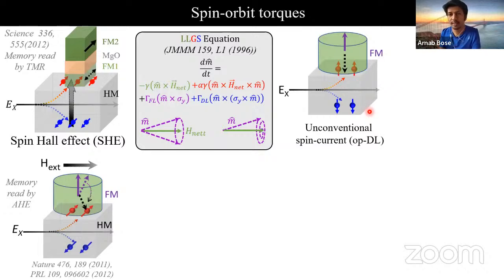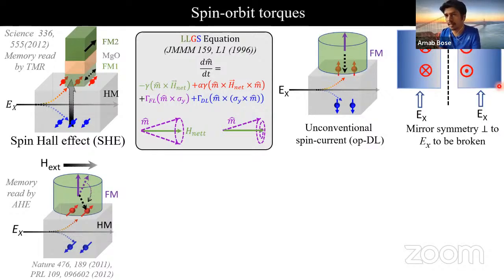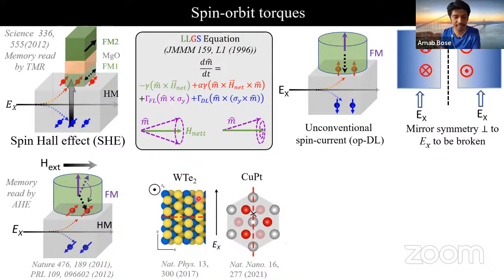Now, naturally, the question arises in which materials we expect such a thing to happen. So now let's assume we have a material, and when we apply in-plane electric current, let's assume that it generates out-of-plane spins. Now, by taking the mirror inversion, we see that the polarity of the accumulated spins flips, but not the electric current. That means it will not be allowed in most of the polycrystalline materials. However, if you break the mirror symmetry perpendicular to the direction of the applied current, this would be allowed, as reported for the first time in tungsten ditelluride and also recently in different types of single crystal materials.